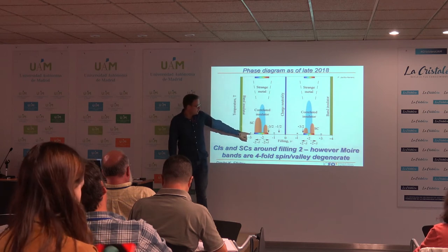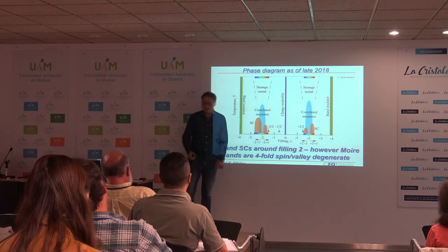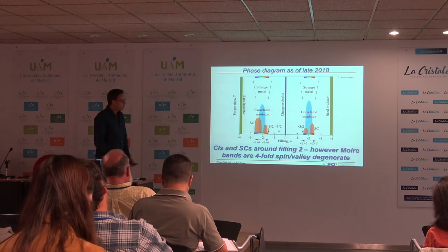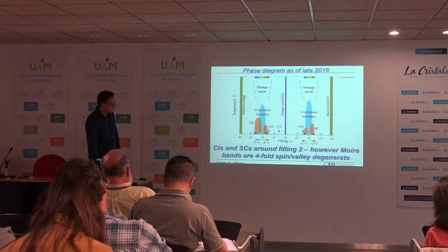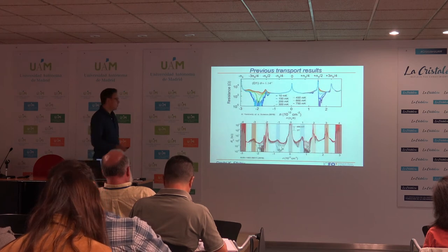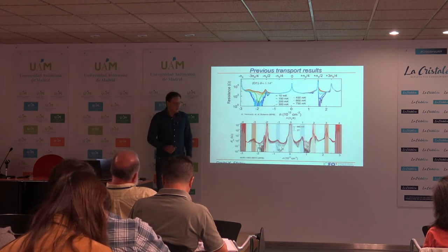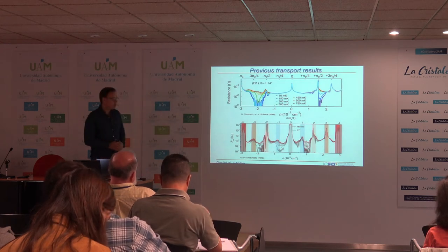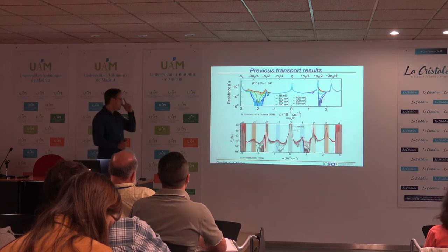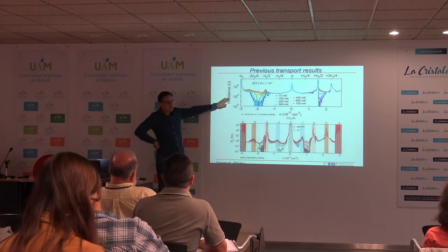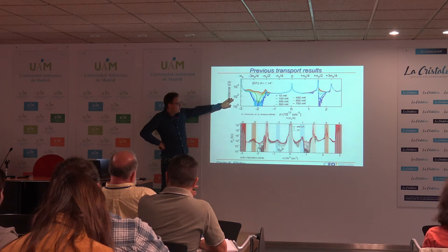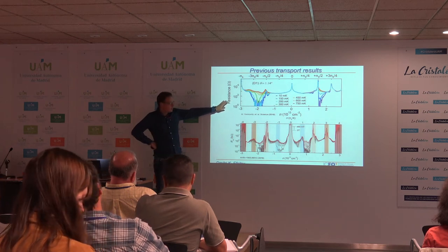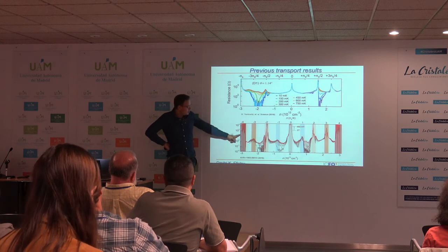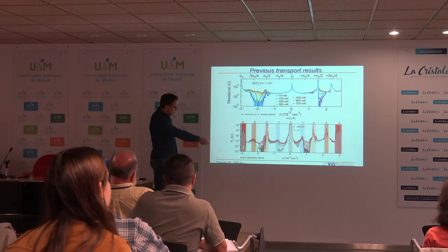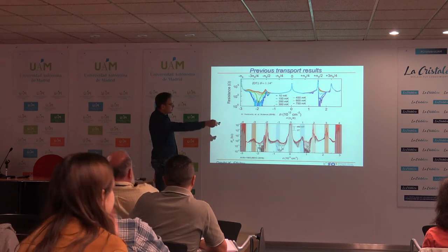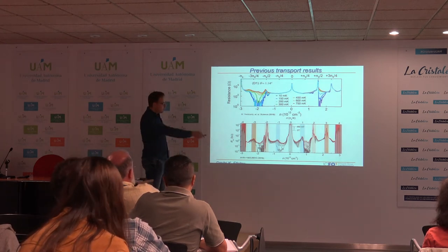And as Pablo already marked, the stars here correspond to notable measurements. So now this is a measurement from the devices which we made. These devices are much higher in twist angle and homogeneity. And what you can see when you compare it with the results from the Columbia group is that a lot of the features are actually the same. So again, when we sit at the edges of the moire band, we get these insulators. So these are the locations here and here. This corresponds to these locations here. So this is the same.